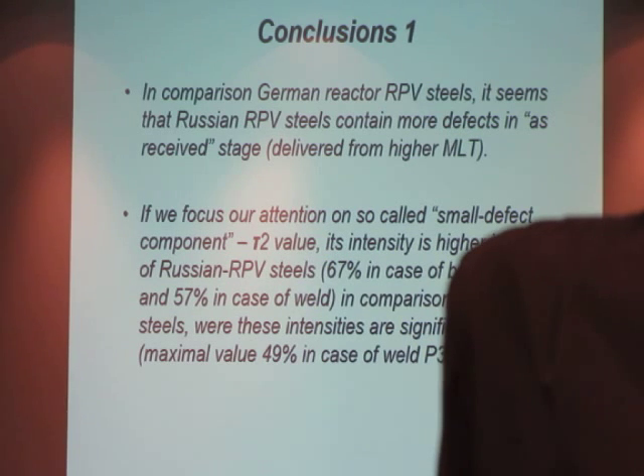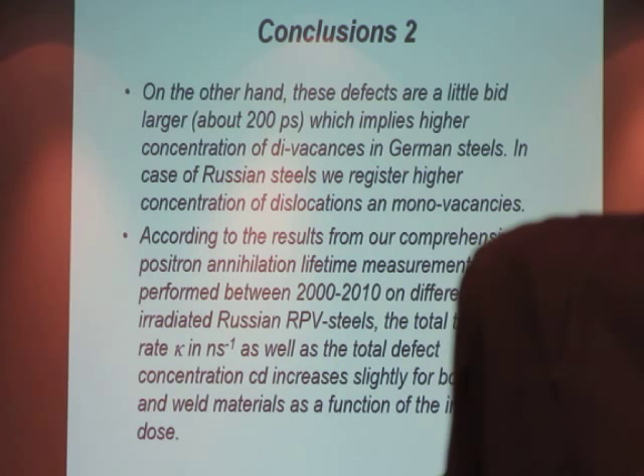In comparison between reactor pressure vessel steels of these approaches, with different chemical composition, we can state that the Russian steels have perhaps smaller defects, mostly dislocations and monovacancies, in comparison to the German steels, where higher defect lifetimes up to 200 picoseconds appeared. But the concentration of these larger defects in the case of the German steel was smaller. 200 picoseconds means that there should be some divacancies as well. In the case of the Russian steels, it was mostly dislocations and monovacancies.